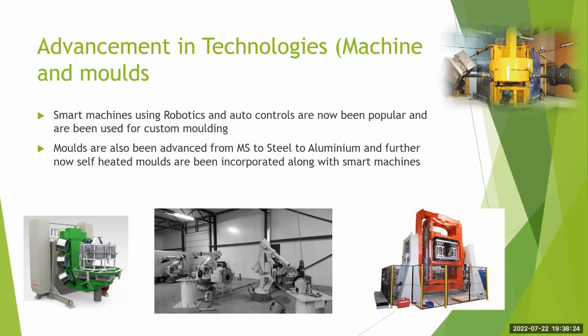The smart machines have a very compact size, and the molds are self-heated by electrical heating or oil heating, and you don't require your own structure there, saving a lot of area. And since the temperature controllers can vary the temperature in different zones and areas, you are also able to clearly monitor the product thickness and the flow of material. This is a very important thing, and you will be able to control it and get product repeatability to much closer tolerances.